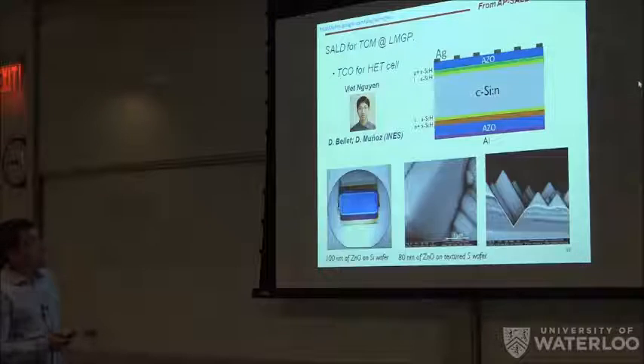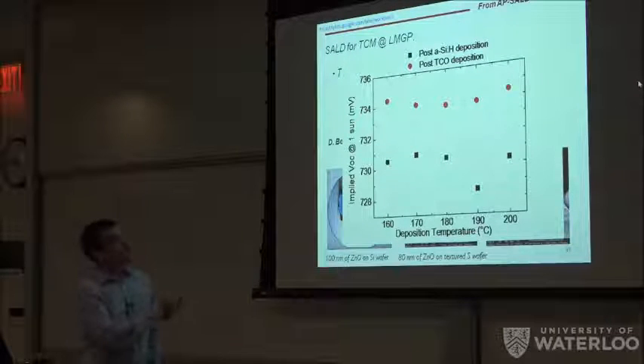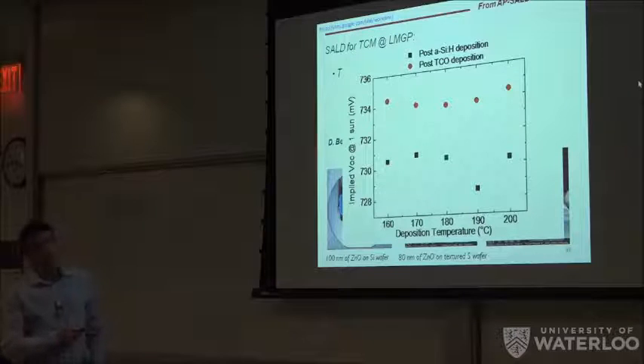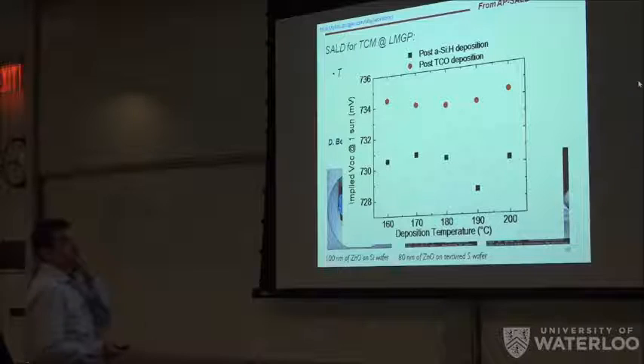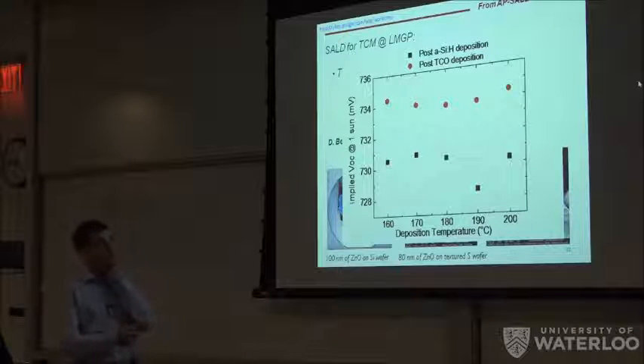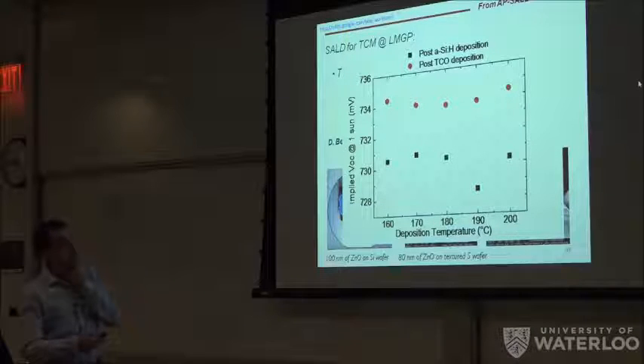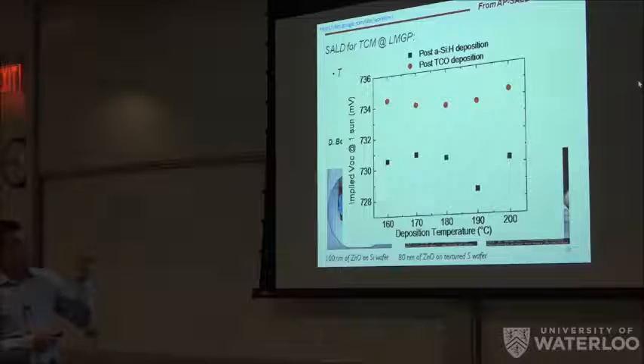And I have it twice, so here we go. So the first results, we're still optimizing the layers, the electrical properties and optical properties of the layer, but already from the passivation point of view, we see that after depositing the amorphous silicon layer, we have a good open circuit voltage. But after depositing the zinc oxide layer with our spatial ALD, we even improve it.